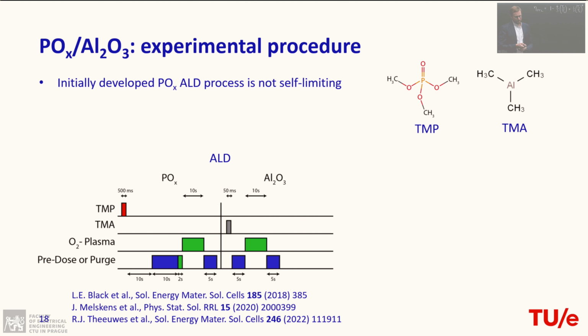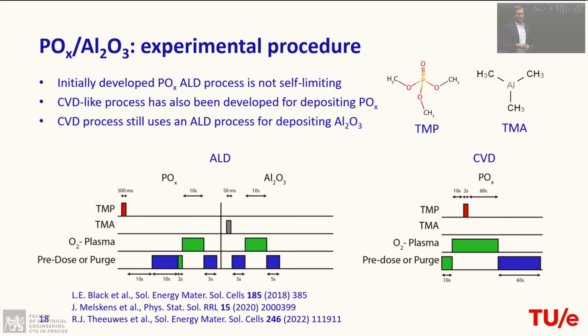So the recipe details are over here. You have basically cycles. In atomic layer deposition, you don't bring all your precursors or reactants together, but you do it in a sequence. And we use these precursors over here, TMP and TMA for the aluminum oxide. The initially developed process was not self-limiting, meaning that the growth still keeps on going when you inject more precursors. So in that sense, it's not a pure ALD process, which already raised the question, is it not better to go for a CVD-like process where you purposely put all the reactants together anyway, because then the growth can also be quicker, and it is easier to make it with other kinds of industrial equipment, which is also familiar with CVD. So we went for that route.